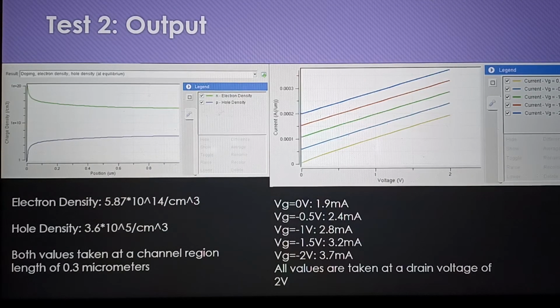So for test 2 output for the electron density at 0.3 micrometers, I got 5.87 times 10 to the 14th, and for hole density, I got 3.6 times 10 to the 5th. The densities seem to be as far apart as they were in the baseline, so yes, changing the dimensions affects the densities of electron and hole being closer or farther apart from each other, but the graph seems to be a lot smoother. There's not a lot of drastic changes of densities over the position of the channel region length.